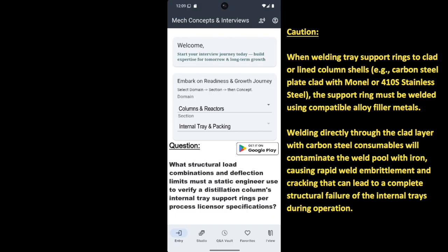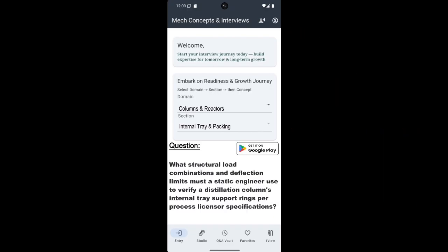And if they use standard materials? If a fabricator carelessly attempts to weld directly through the clad layer using standard carbon steel consumables, it immediately contaminates the weld pool with iron from the backing plate. Iron dilution. Yes. This iron dilution causes rapid weld embrittlement and cracking, leading to the complete structural failure of the internal trays under pressure.